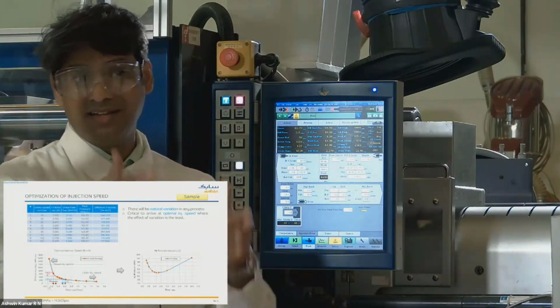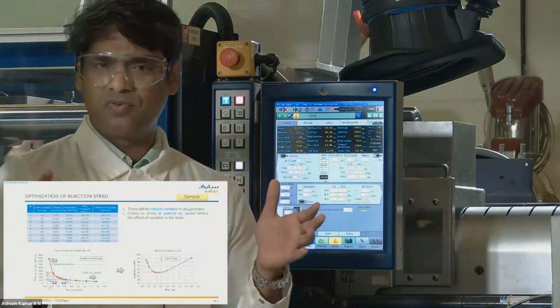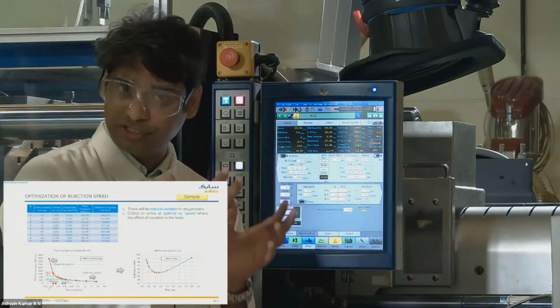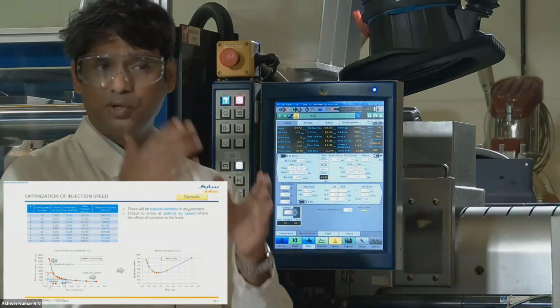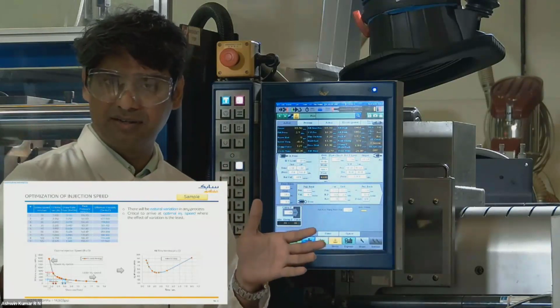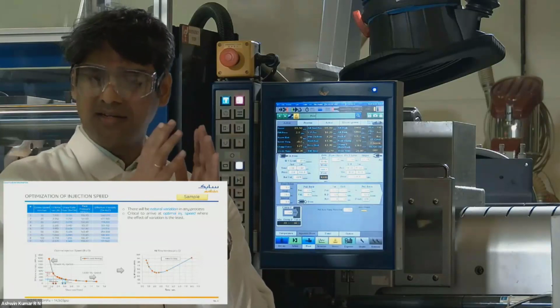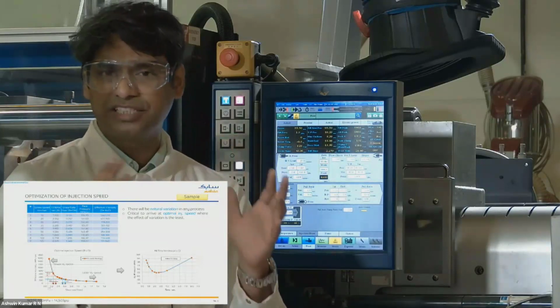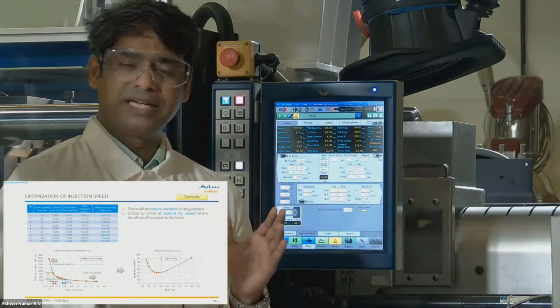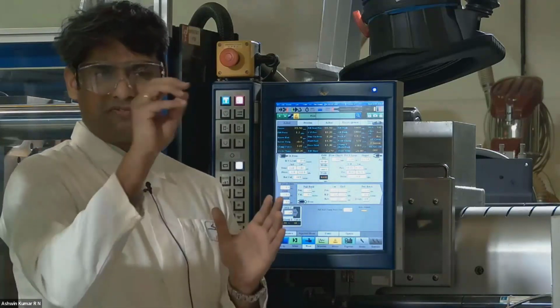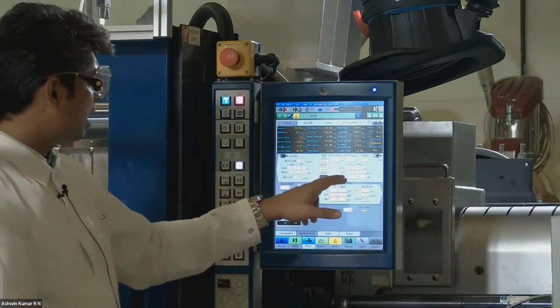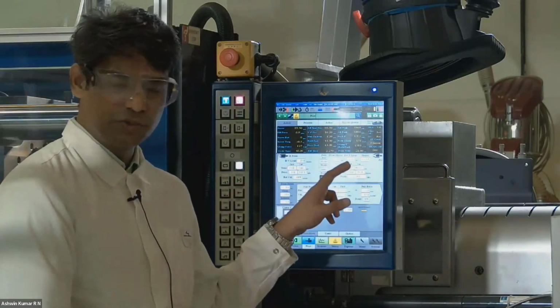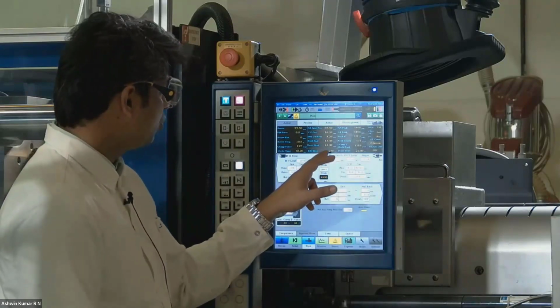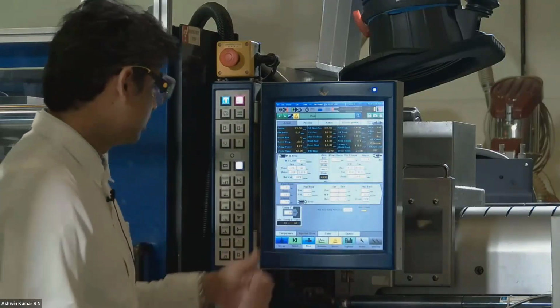And as you can see, that is a typical curve from this boundary system of the design and the tool. You get a similar curve to what you see there, and we pick the lowest range where the variation is not much influenced by any changes in the environment. So with that, we fixed about 35 mm per second as a screw speed, and that is resulting in about 2.2 seconds of fill time for this kind of part.